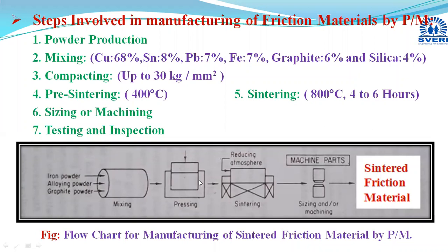Pre-sintering and sintering both are done in a controlled reducing atmosphere. Here pre-sintering is done to remove the oil, whichever oil we have added, to give the necessary uniform and homogeneous mixture and to help in the compacting or pressing stage. That oil added is eliminated by heating the component at 400 degrees Celsius. After that, it is subjected to the main sintering operation.